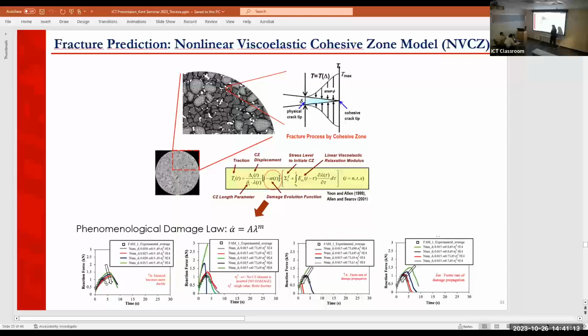In this study, you can see later on in this paper that each of the model parameters affects the way the force displacement curve responds, the response of the material. The higher the delta, it seems like the material becomes more ductile. We reduce the maximum peak load and the fracture energy increases.